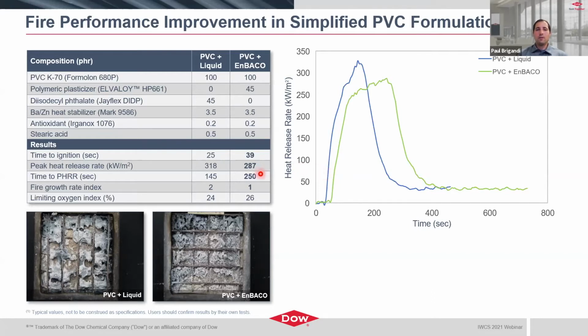liquid. Those two combined together, typically give another parameter that is calculated in the industry, the fire growth rate index. In this case, you see we have a 50% lower, half the fire growth rate index with the PVC plus the polymer modifier. If you think about it, it's giving us a longer time to ignition as well as a lower peak heat release rate, or lower energy for that fire. And so it's more resistant and much better when you think about time to escape in the unlikely event of a fire in a building with cables jacketed with such material.